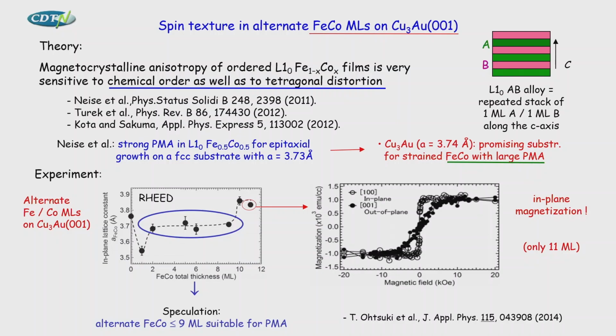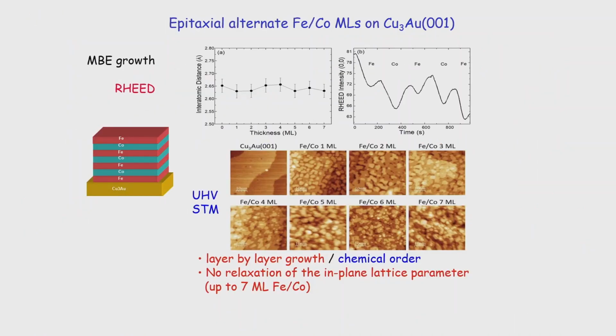They have grown this kind of material, alternate iron cobalt monolayers, but they measured the magnetism only for 11 monolayers, and they saw in-plane magnetization. And they speculate that RHEED, which gives you a measurement of the structure of the sample, showed some change in the structure at 10 monolayers. They claim that the magnetic measurements were done after this transition. That means if you are below it, we should see perpendicular anisotropy. And this is what we decided to look at: to grow iron cobalt alternate monolayers on Cu3Au below 10 monolayers, okay?